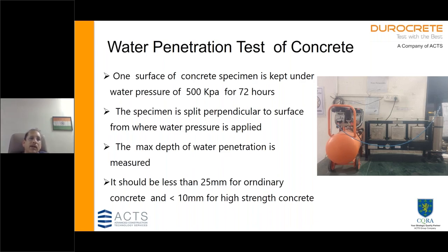So here the concrete specimen is kept under water pressure of 500 kPa for 72 hours, and then after 72 hours the concrete specimen is split wide open, and we measure the depth of penetration of water. The standard says that it should be less than 25 mm, but generally for high grade concrete it is recommended that it should be less than 10 mm. If you are having very good concrete, you will generally have 3 to 4 mm penetration.